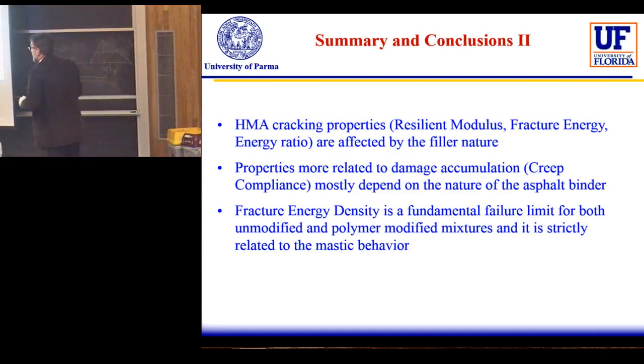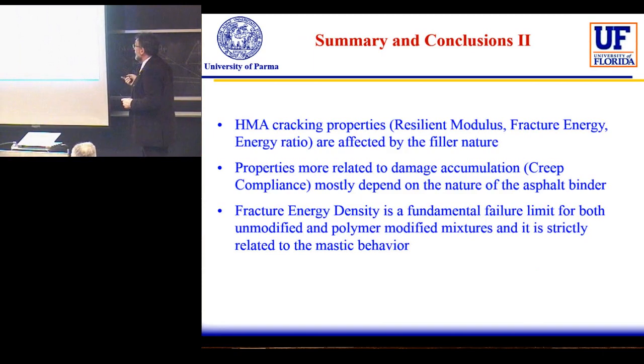So, in conclusion, HMA cracking properties are affected by the filler nature. The message to the people that design the mixture is that filler is not something that you have to buy on the market by following the cheapest one, but something that needs to be considered due to the effect that it has on the behavior. The property seems more related to damage accumulation, and depends on the nature of the asphalt binder. And again, the fracture energy density can be considered, and this is a very strong affirmation, a fundamental failure limit for both unmodified and polymer modified mixtures, and strictly related to the mastic behavior.